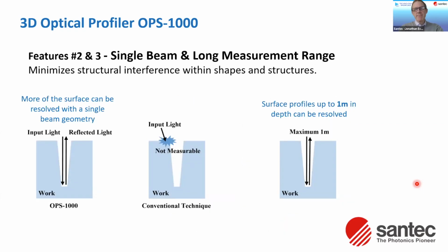Features 2 and 3, the single beam geometry and long measurement range, kind of go hand in hand. Traditional metrology systems may have a light source and detector separated in space. So you get into this kind of instance where surfaces will be occluded from the light being able to reach the detector. Whereas if you're using a common path for both your analyze and detect beams, you can see deeper into the object. And the fact is we can set up the coherence length of our system. So we can go up to 1 meter in imaging range in depth, which is far larger than the other systems out there.